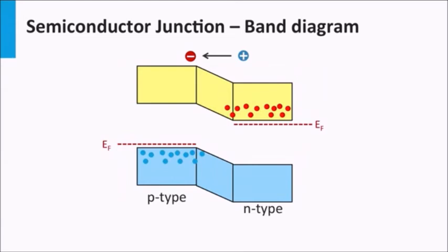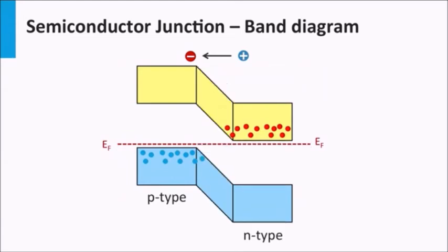This is demonstrated in this animation. If we equalize the Fermi levels, the conduction and valence band are bent in the depletion zone. We see that in thermal equilibrium, the valence and conduction band have a steep slope across the depletion zone. As discussed earlier, a slope in an electronic band diagram represents an electric field.